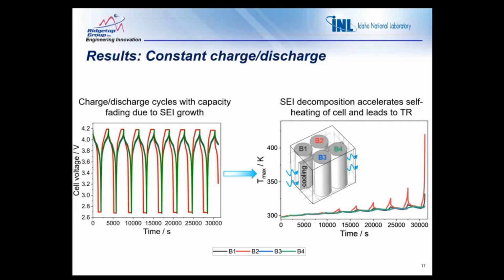On the right hand side, we focus on the temperature behavior of the cells within the module. The SEI decomposition and exothermic reaction plays a critical role here. As the SEI breaks down, it releases heat, leading to self-heating of the battery. This accumulates over cycles, causing an exponential temperature increase as shown in the Tmax, or the maximum temperature versus time plot. The temperature rise accelerates over time due to exponential dependence described by the Arrhenius equation.